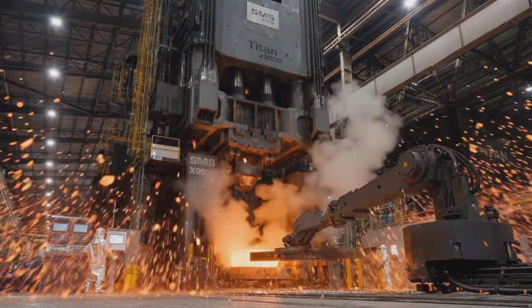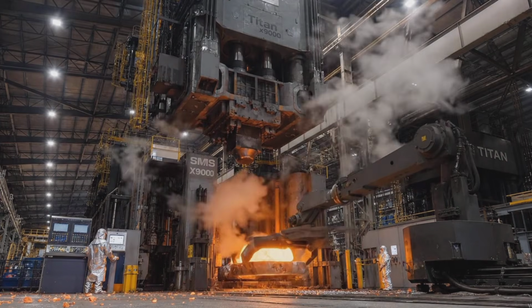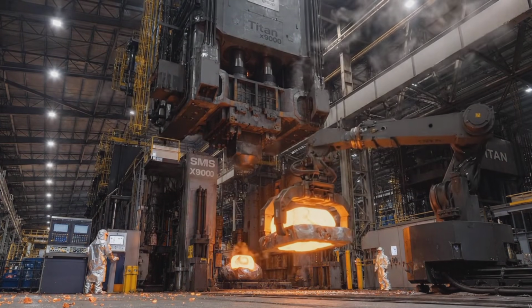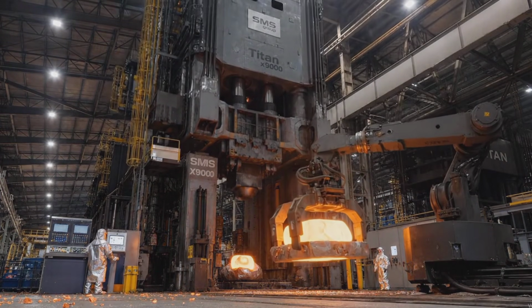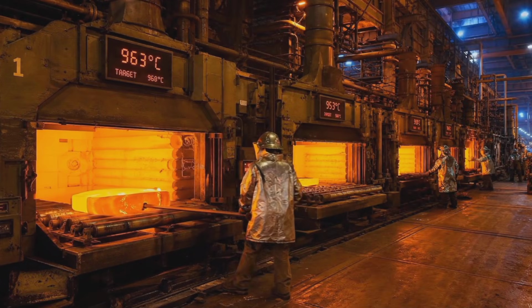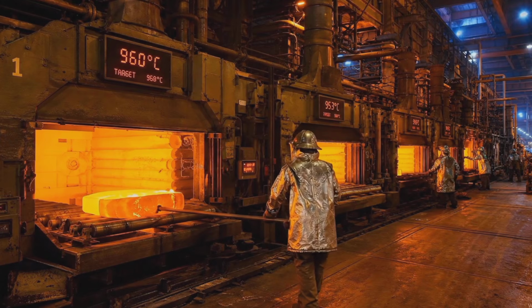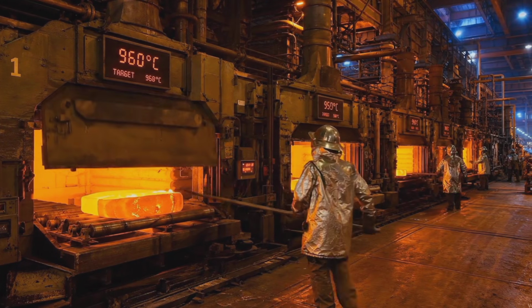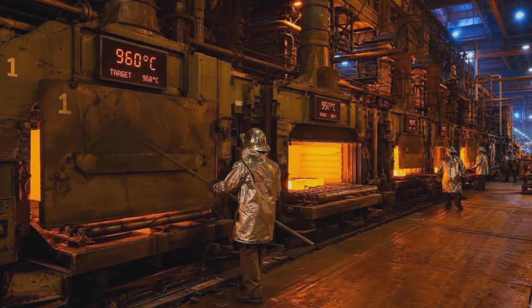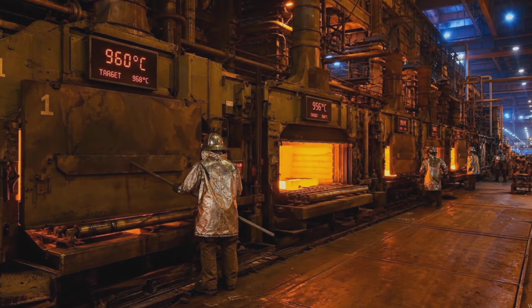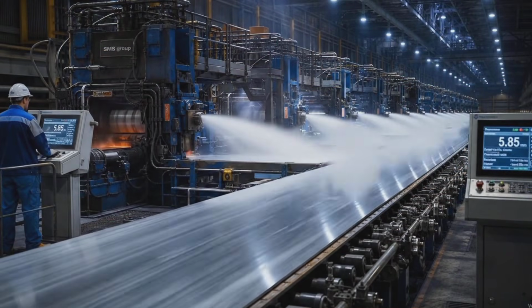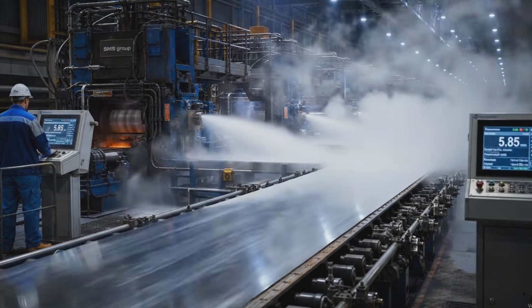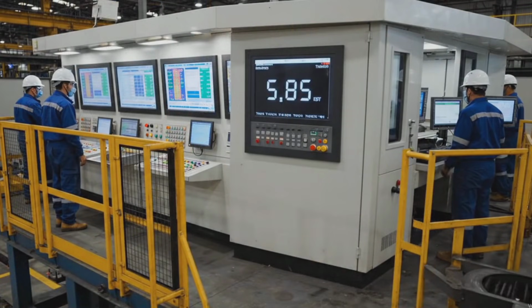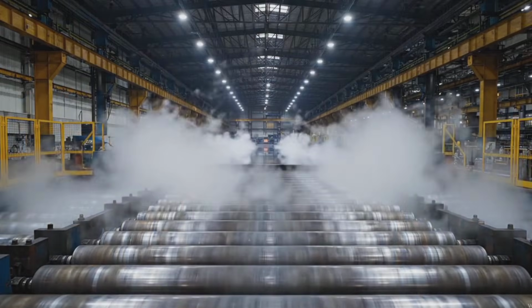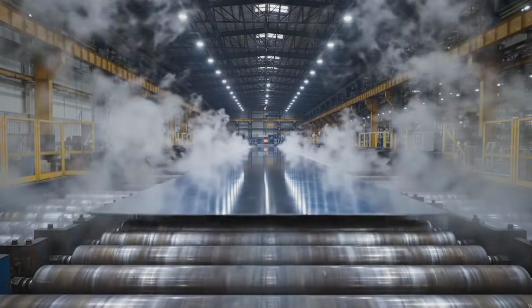After cooling, the ingots are inspected. Ultrasonic scanners probe deep into the metal. Every crack, every void, every inclusion must be found before moving forward. Then, in reheating furnaces, the ingots reach forging temperature and are shaped under enormous presses. The hot gray metal is transformed into slabs and billets, and hot rolling stretches it into long, thin plates, silver, gleaming, ready for the next stage.